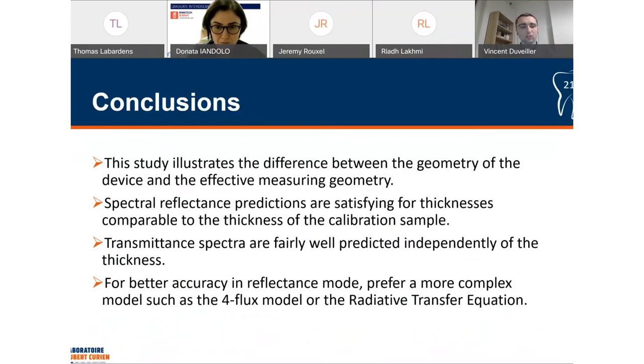We definitely think that it will provide an improvement because the Kubelka-Munk model can only consider either the collimated fluxes or the diffuse fluxes. But in fact, the reflectance would be more accurately predicted using the diffuse fluxes, while the transmittance would be more accurately predicted using the collimated fluxes. So a model that can take both types of fluxes into account, like the four-flux model or the radiative transfer equation, would definitely provide huge improvements.